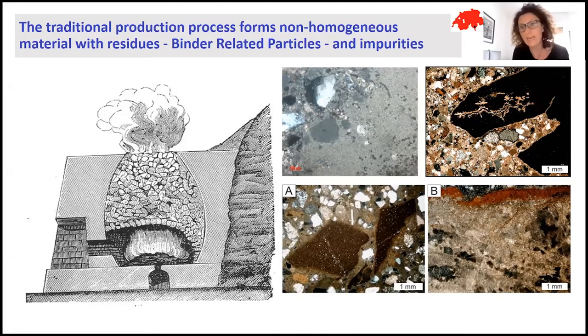On the other hand, we have the stones which are very close to the fire, and in this case we can have the overburned particles. The overburned particles are particles that reach too high a temperature, and in this case we arrive at the fusing or sintering of the lime. So when I find a lot of this kind of particles in a mortar, the information is that the production process was not so efficient, because I have used a lot of energy, a lot of fuel, a lot of resources just to have a non-reactive particle. So the process in this case is not so efficient.